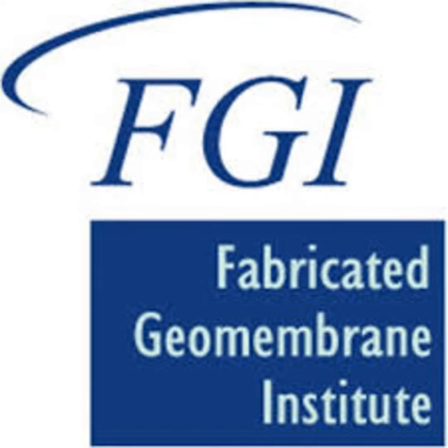Most studies, the second part of this question was talking about anoxic versus oxic environments a little bit. Most studies, to my knowledge, that have looked into polymer degradation have focused on degradation in oxygenated environments. It's a little bit easier to control, and we know that oxidation happens, as compared to anoxic environments. But in liner systems, there's going to be limited oxygen. So that's again a different environment that we need to evaluate to look at degradation.